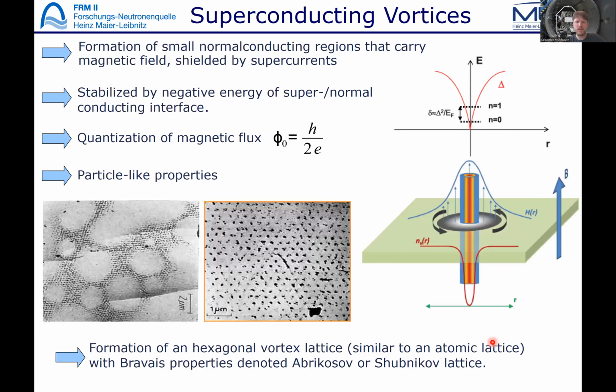What happens is you have a small normal conducting area which carries the magnetic field, shielded by a supercurrent, and this normal conducting area is called a superconducting vortex. Due to the quantization of the magnetic flux, each vortex carries exactly one flux quantum. So this is the vortex flux quantum h/2e, and this is the flux of a superconducting vortex. And it's geometrically shown here.